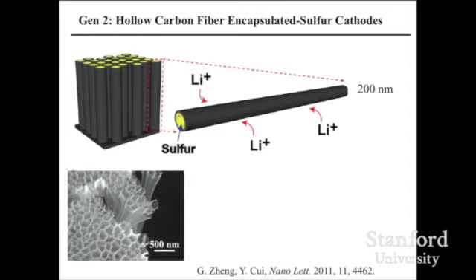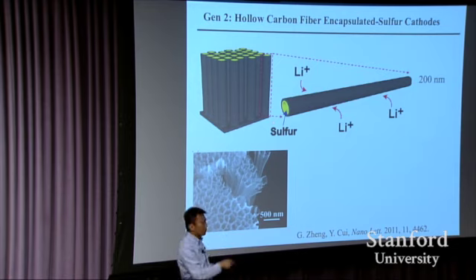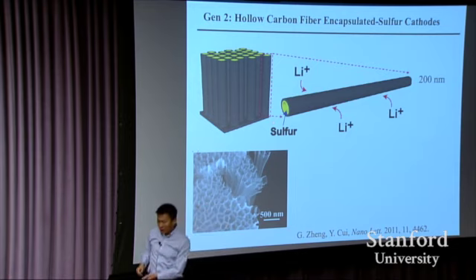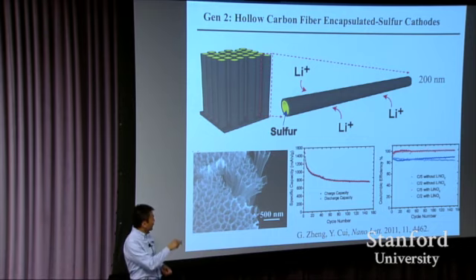When Wesley joined my group, we started to develop these hollow carbon fibers to embed the sulfur inside. Sulfur has volume expansion. Let's embed it inside, leave some empty space right there, just like silicon. The expansion is inside. The polysulfides are captured by this hollow carbon fiber, only leaking out from two ends. By doing this, we at least can improve the performance quite a bit. Yes, it does, but still decays.